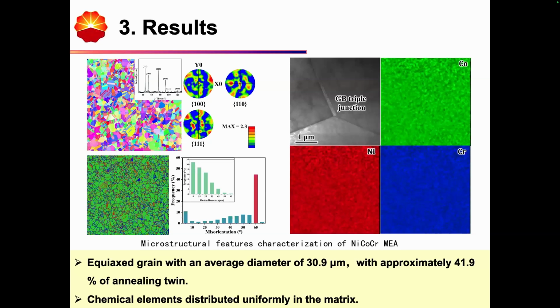Based on the XRD test and the EBSD test, we obtained a single FCC phase medium entropy alloy with an average grain diameter of 30.9 micrometers. Due to a relatively low stacking fault energy, the annealing twin percentage is about 41.9.